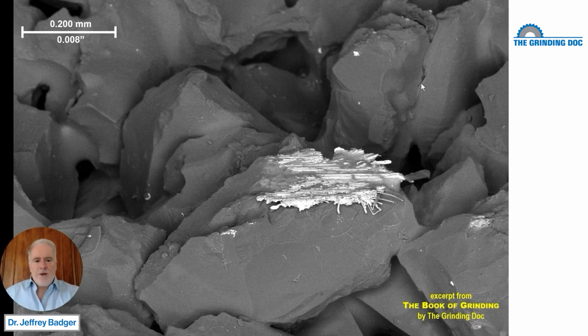Then when we turn on the backscatter effect on the electron microscope, what we see is steel stuck to the grit. So we have little chips that are stuck, and then those chips compacted, and then those chips started chemically reacting with the aluminum oxide or the iron oxide layer. And what we have is a layer of smeared material, smeared steel, smeared workpiece material on the top of the aluminum oxide grit. We don't want to grind with this. This is going to be pain and suffering. And it's pain and suffering because we have a loaded wheel.